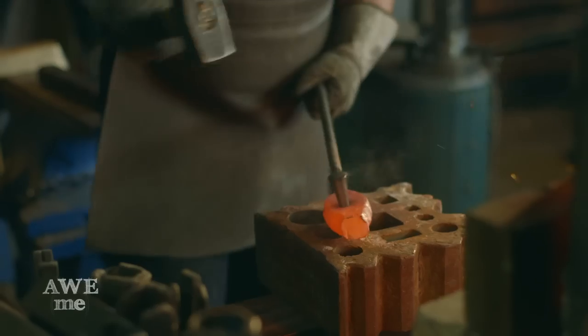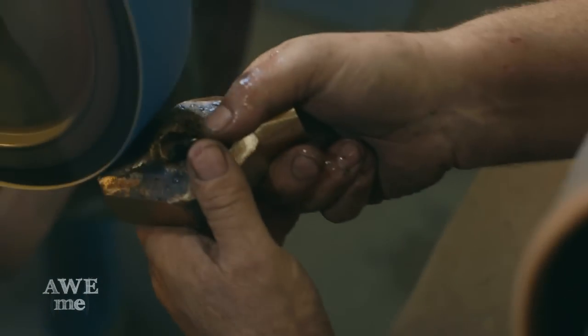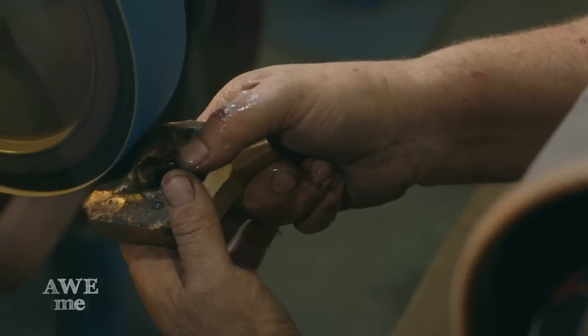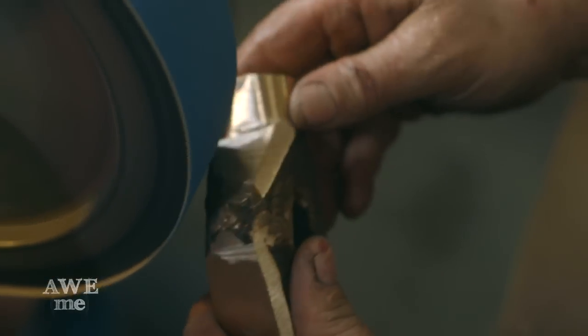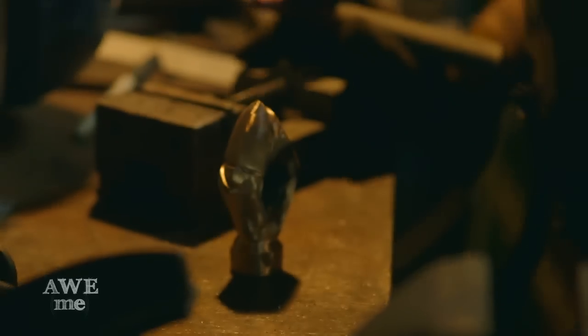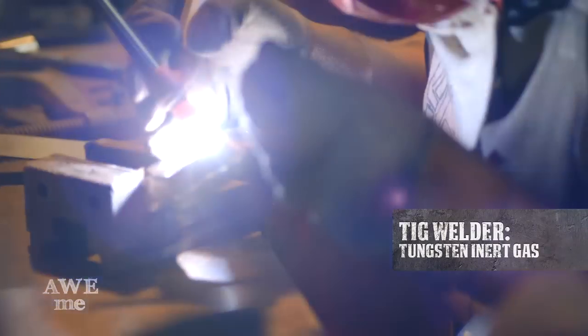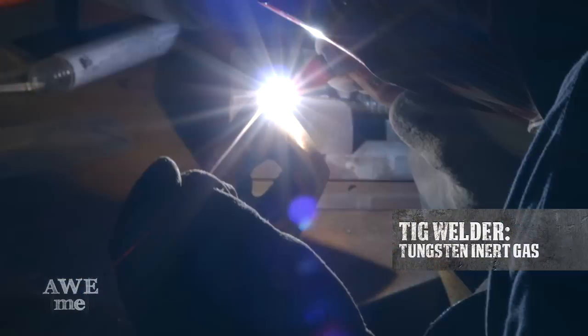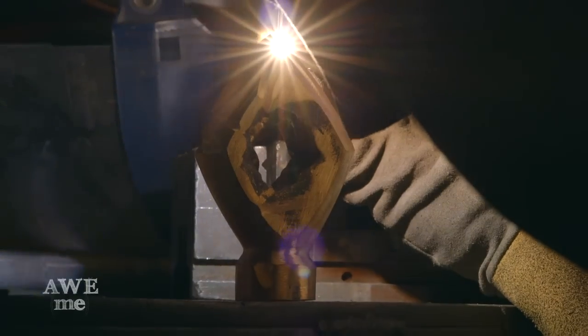I cracked it in a couple places because bronze is not really a material that's conducive to hot forging, so it got a little bit too hot and separated, but it does weld very easily, so I was able to TIG weld it with bronze welding rod and got everything cleaned up. There was an imperfection. The welding made it perfect again.